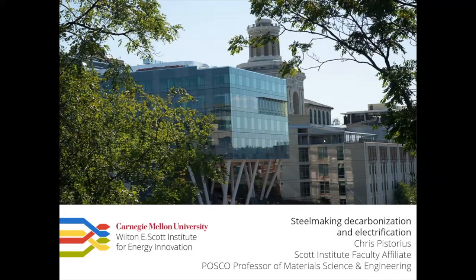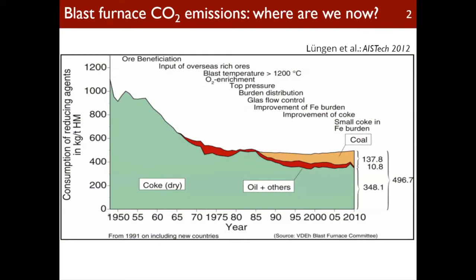So in 10 minutes or so, just a few perspectives on where we are and where we need to go and some of the challenges of getting there. In terms of where we are right now, the global iron and steel industry is very carbon intensive, really because of the reliance on blast furnace iron making. This chart shows the historical development of how much coke primarily is used in blast furnace iron making. And what it does show is that the industry has been pretty good at optimizing the blast furnace. But from the leveling out, you can see it's gone about as far as it can, given the thermodynamic limitations.